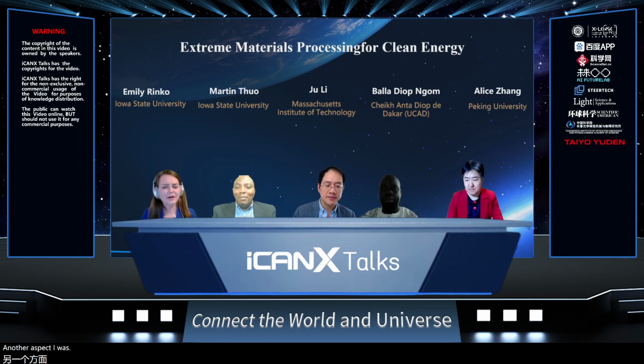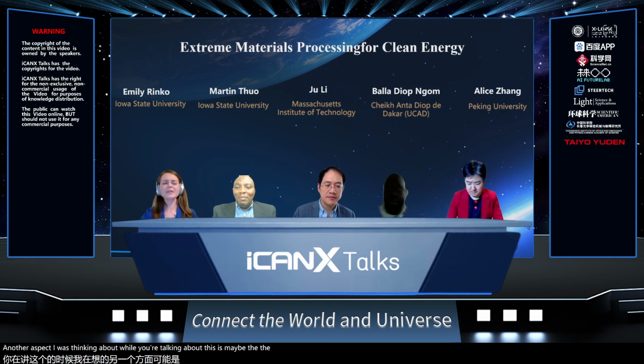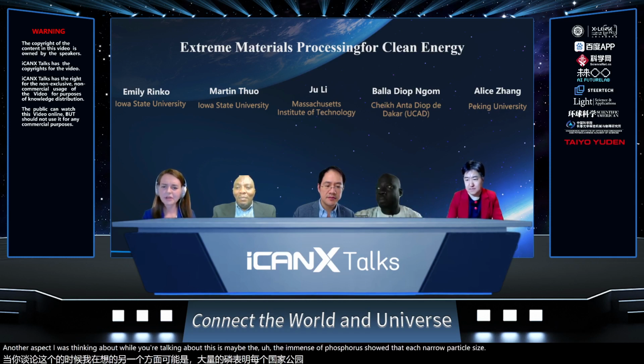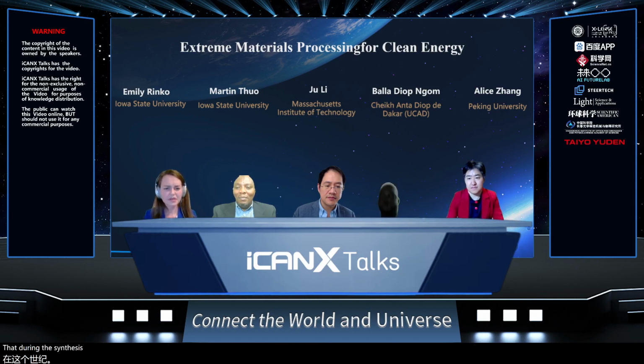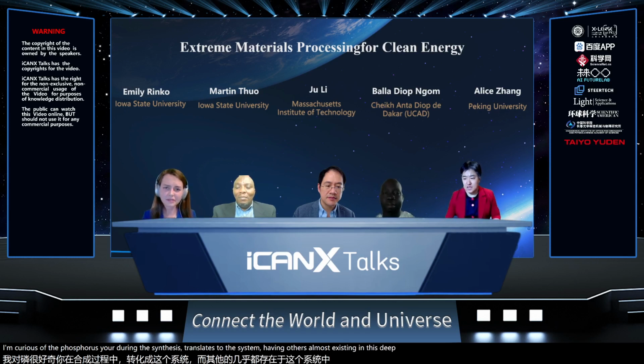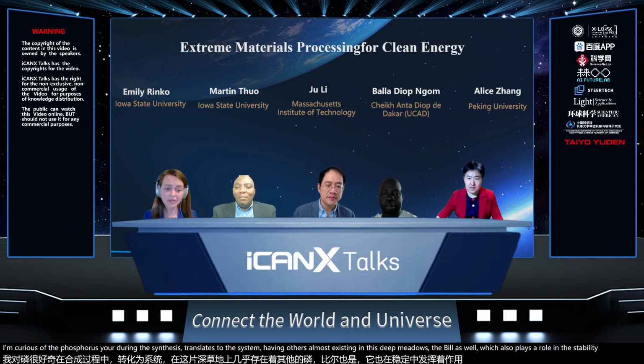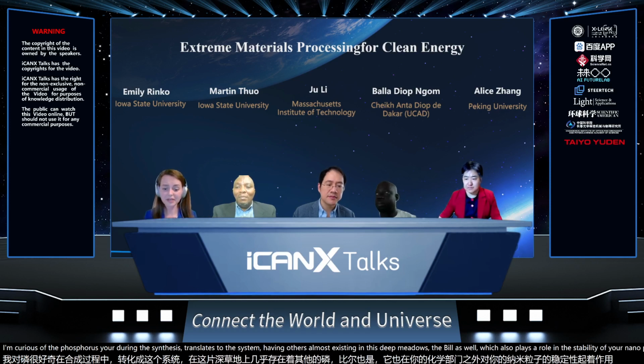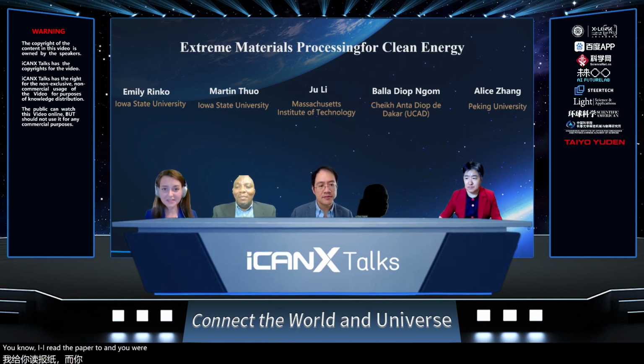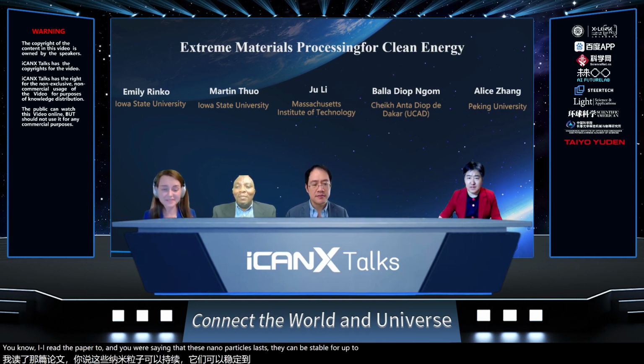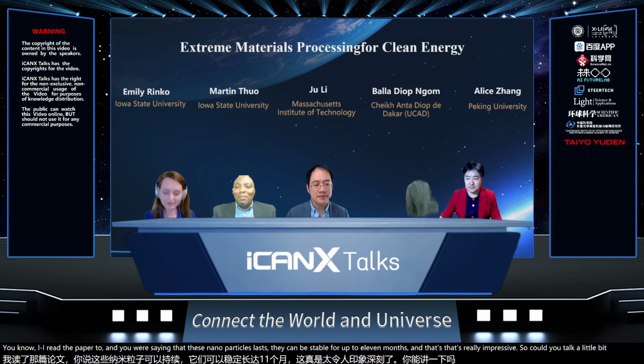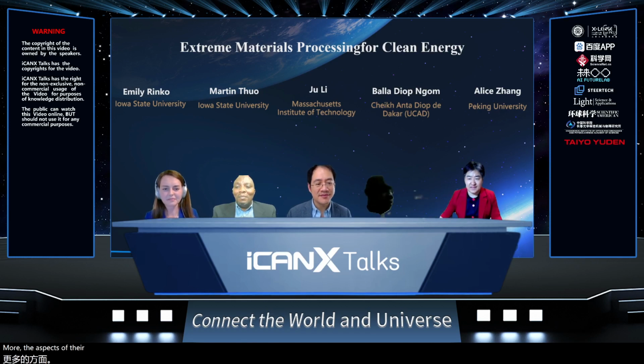Another aspect I was thinking about while you were talking about this is maybe the immense Laplace pressure that each nanoparticle felt during the synthesis process. So on top of the rapid cooling that you just mentioned and the catalytic process, I'm curious if the Laplace pressure during the synthesis translates to the system existing in a deep metastability well, which also plays a role in the stability of your nanoparticles outside of your chemical uniformity. I also read the paper too, and you were saying that these nanoparticles can be stable for up to 11 months. And that's really impressive. So could you talk a little bit more about the aspects of the stability? Maybe would Laplace pressure also be part of that as well?